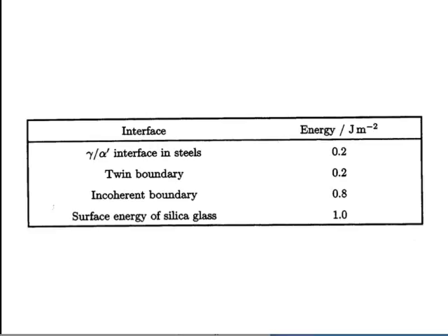Okay. And if you go back to your example of FCC to HCP, do we satisfy that condition? The basal plane and the close-packed planes are completely coherent between HCP and FCC, right? The 1-1-1 plane is exactly the same as the 0-0-0-1 plane of HCP. So we satisfy the condition because every line in that plane is an invariant line. Everyone happy with that?